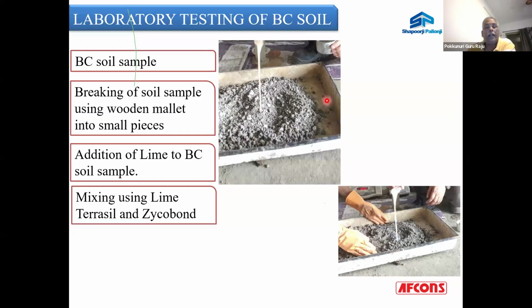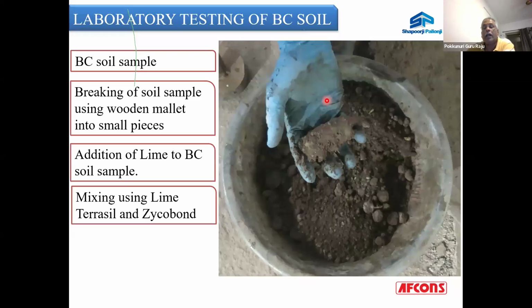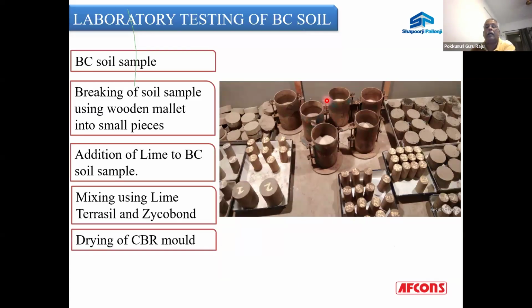Once you add Terrasil and Zycobond, you can check the availability of the water, the moisture level, because that is what is required before casting the proctor molds. And then once it is cast, it is allowed to dry and cure for 4 days. Why? Because cement also demands 7 days curing, but in this particular case also, it develops the strength. So it needs to be dried and cured for 4 days, and after 4 days, if you are testing for CBR, then definitely you are going to get good results.